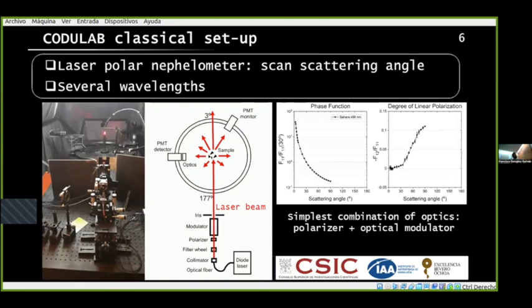This is actually the simplest combination of optics, only a polarizer and the optical modulator in the optical train. And what we see here is that basically towards zero scattering angle, so when you are looking forward in this position, you have the diffraction maximum. And the other very characteristic element of the polarization curve is that at a specific inversion angle, it becomes negative. That means that the negative polarization means that the polarization vector is parallel to the scattering angle.